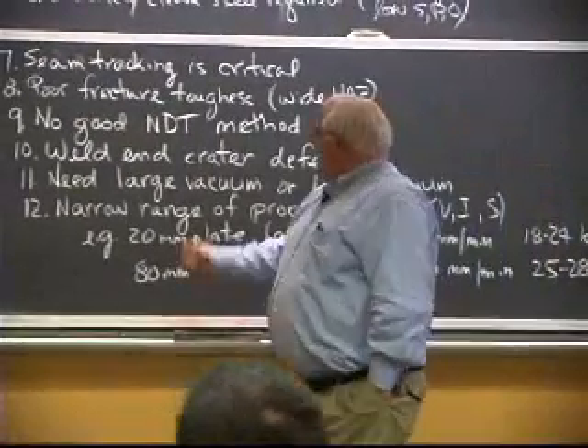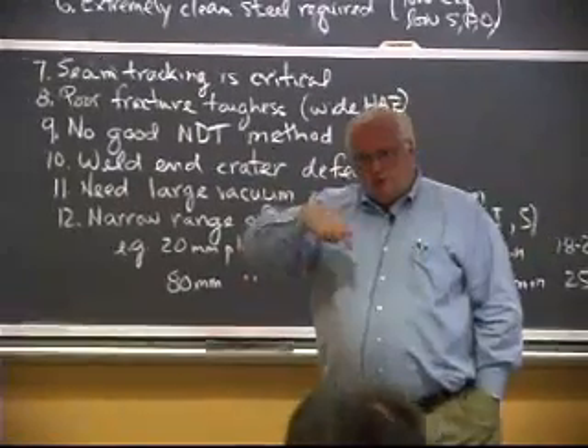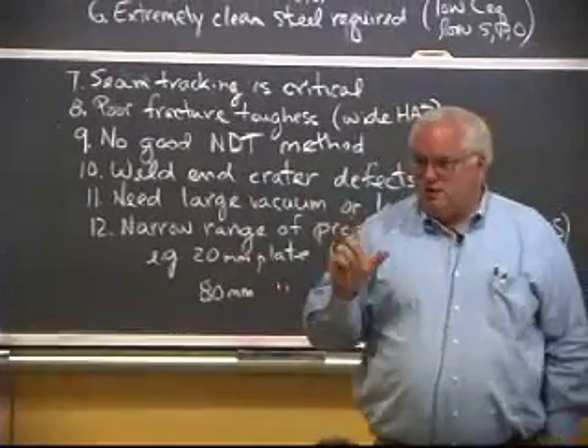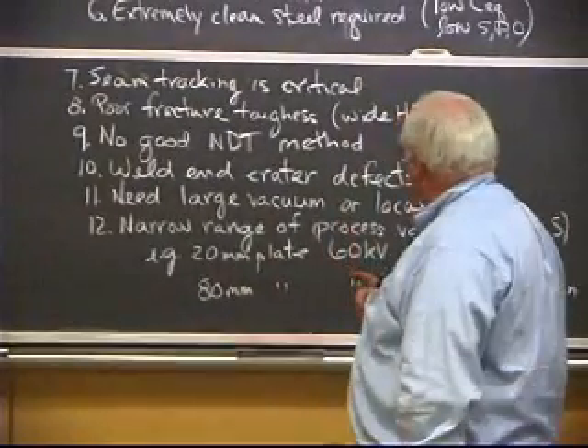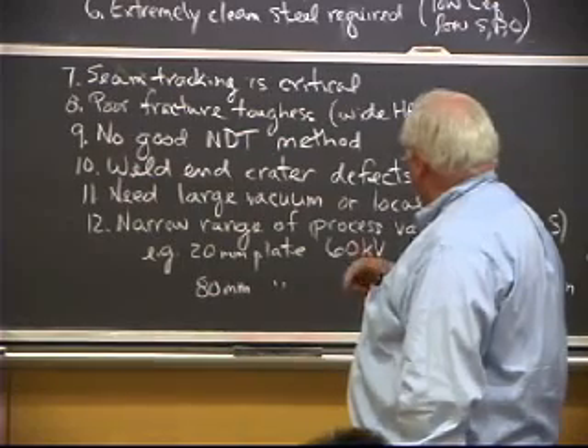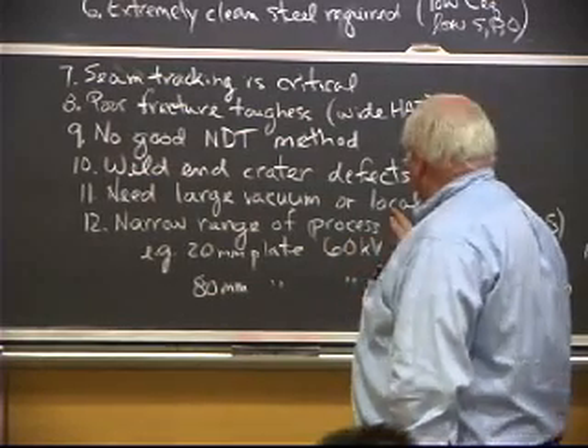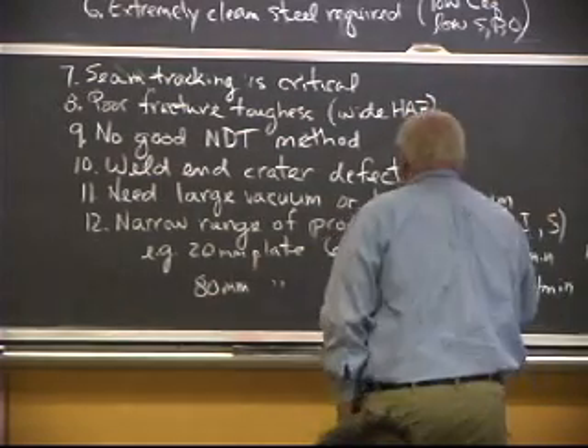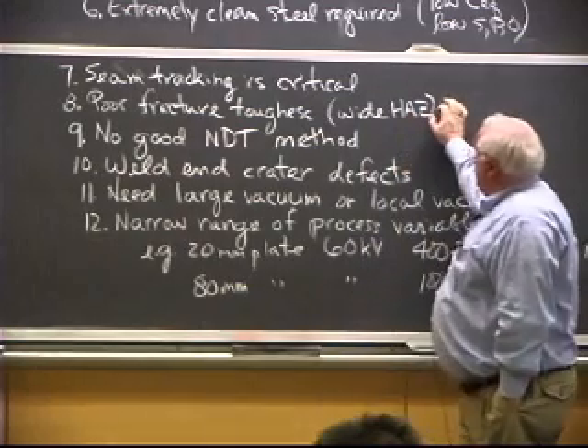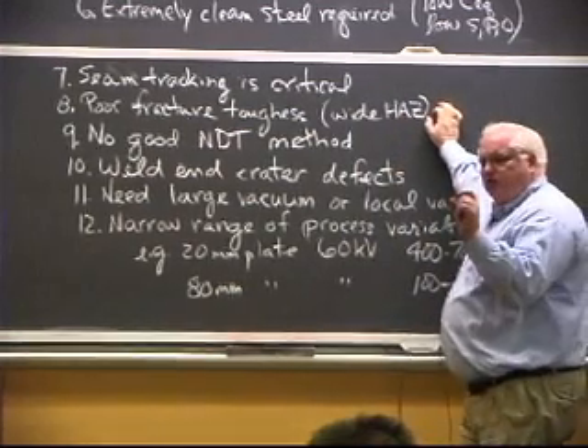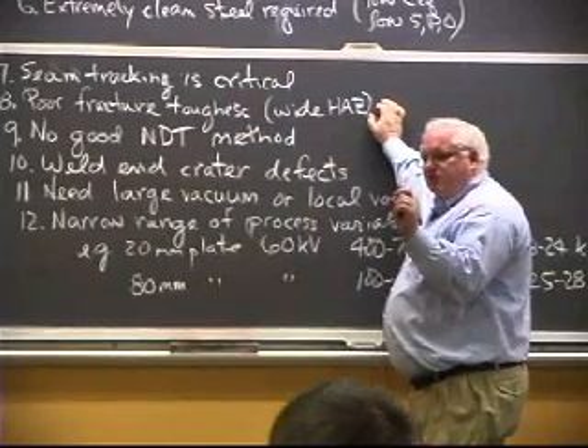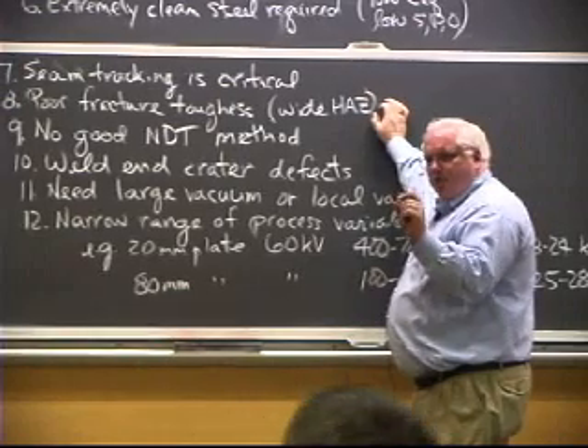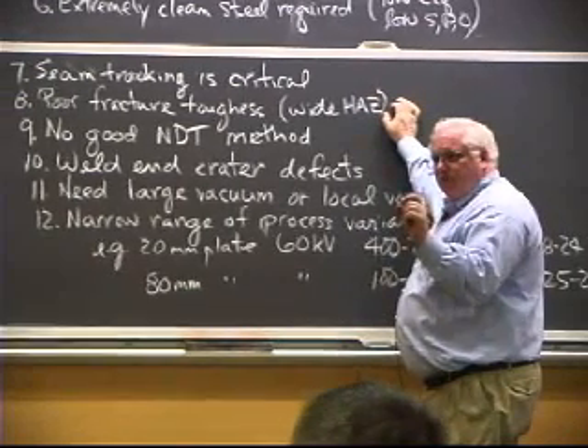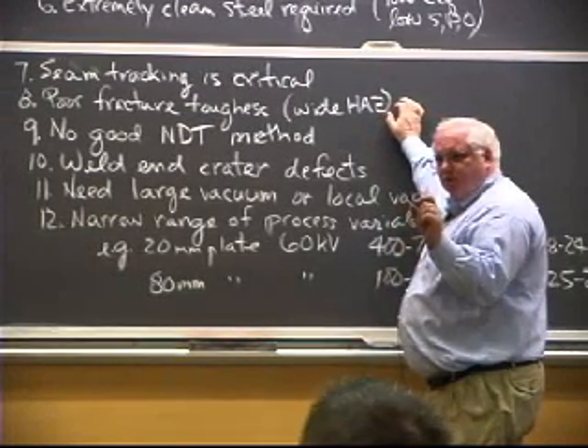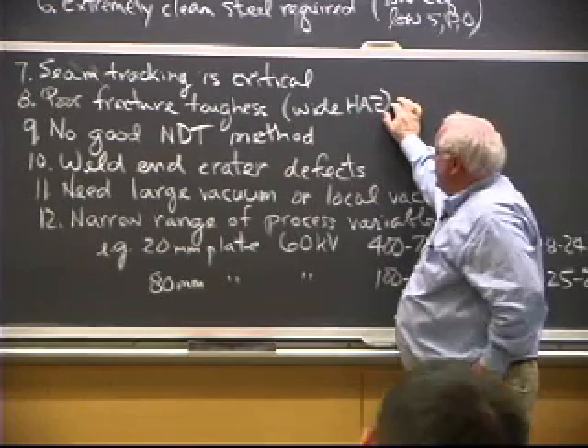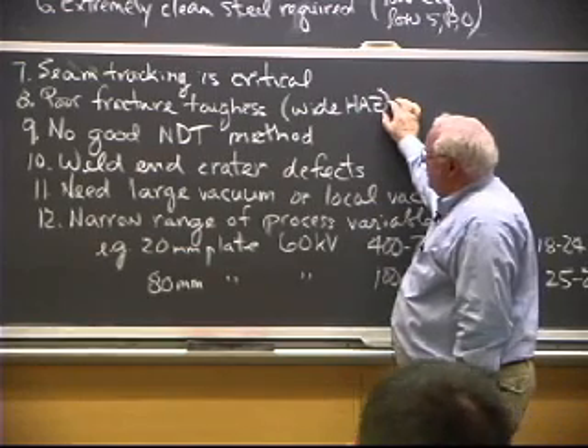Seam tracking is critical. You can't miss the joint. Okay, 8 inches deep, it doesn't take much to be off. Poor fracture toughness, because of this wide heat affected zone: to not miss the joint, at 8 inches thick, you probably need a 2 centimeter wide weld. Well, a 2 centimeter wide weld means a 2 centimeter wide heat affected zone, which means huge grain growth in the heat affected zone, poor toughness.